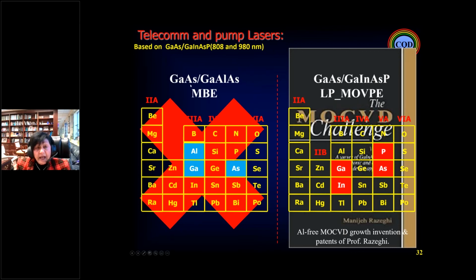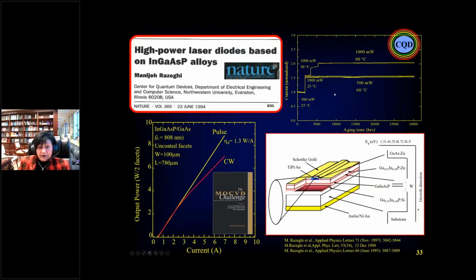For the telecom, pump lasers, and many different applications, they were using gallium arsenide and gallium aluminium arsenide with MBE, which was expensive, and due to the aluminium there was a problem with the material and the laser: it was catastrophic optical damage. What they needed was very expensive. I developed aluminium-free MOCVD epitaxy, and that revolutionized it, exactly as you can see. I did that in 94 and published in Nature, and the lifetime became, as you can see here, forever, with excellent performance for high power lasers.